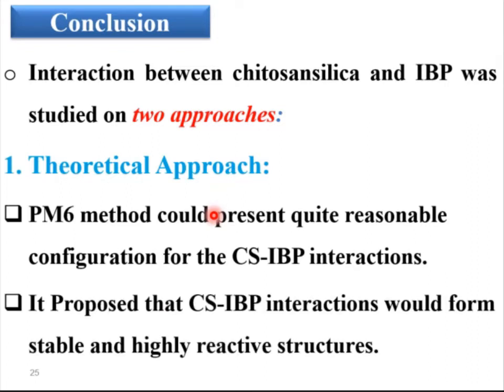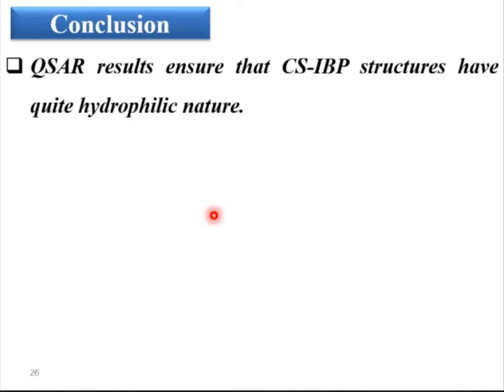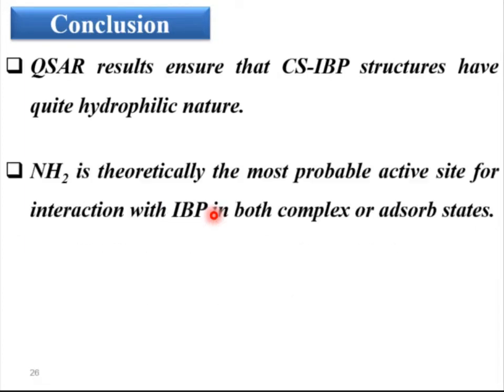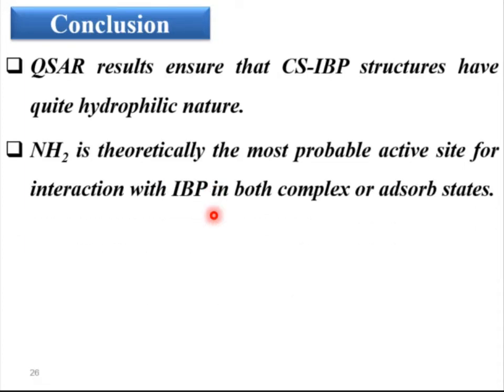Then it was proposed that chitosan silica ibuprofen interactions would form highly stable and highly reactive structures. Also, QSAR parameters ensure that chitosan silica ibuprofen structures have quite a hydrophilic nature. Finally, the amine group is theoretically the most probable active site for interaction of chitosan with ibuprofen, either in a complex or adsorbed state.